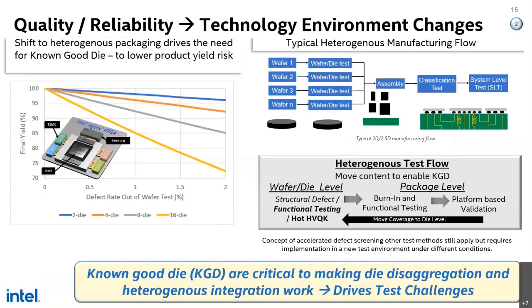One way to do this for heterogeneous applications is we can treat all of the wafers like we've treated them on the previous slide, where you have the progressive defect screening and testing. And when you apply those together in assembly, you can again do your normal testing and do again testing at the final product or system level there. So what we have to do is essentially take all of these known good die, apply the testing at the wafer level, and the stressing at the wafer level, and continue that process for all the known good die to result in a high yielding and a high reliability heterogeneous package that's fully integrated.